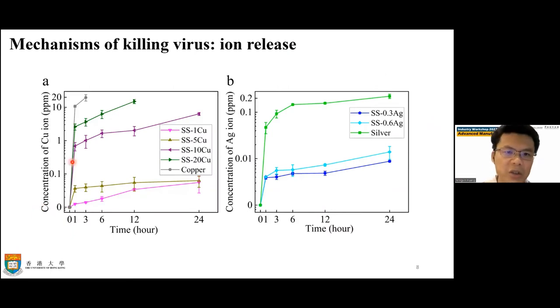And we also check the concentration of the copper ions, okay? We expect that because of the copper ion release, this copper ion reacts with the virus or the bacteria. That leads to the death of the bacteria or the inactivation of the virus. You can see that for pure copper, a few hours later, the copper concentration is very high because it is pure copper itself, okay? But if you have a lower copper content, 1% copper, 5% copper, you see the copper concentration is low. With 10%, 20% copper, it reaches, within a very short time, properties very similar to pure copper. So that explains why a higher copper content can make a better antibacterial or antivirus stainless steel.